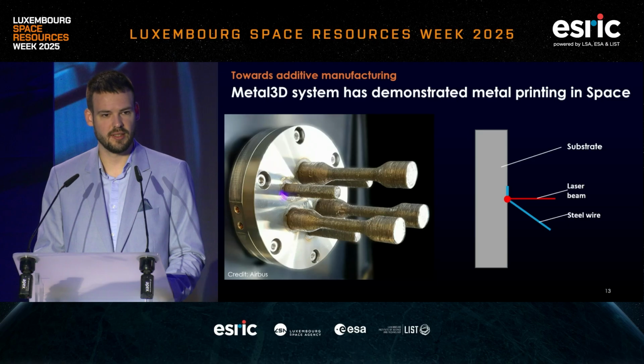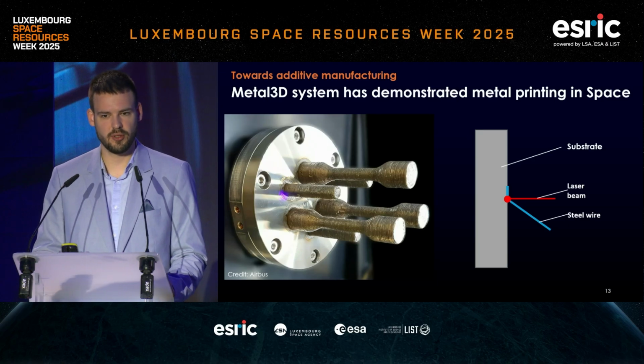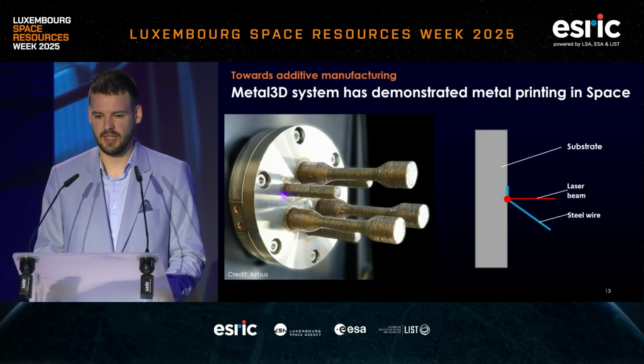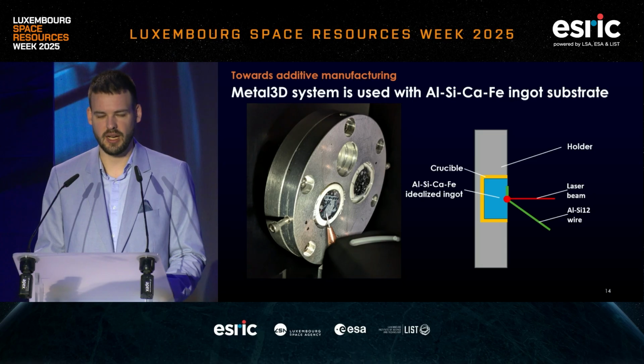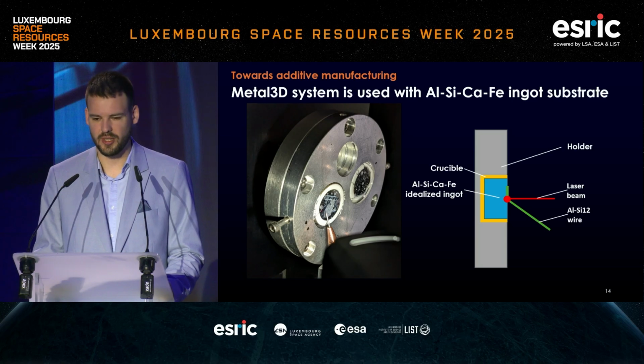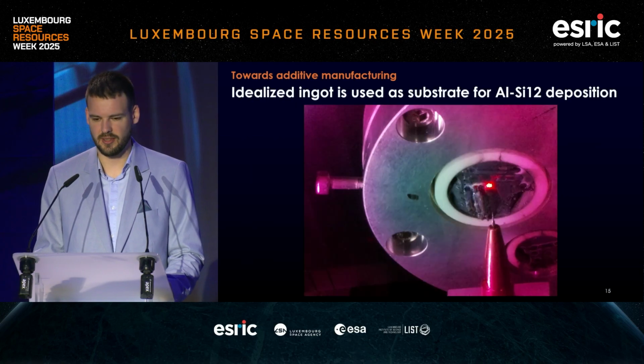So we have been using the engineering model or a prototype of the same system, and we applied it to our idealized aluminum, silicon, calcium, iron mixtures. So we replaced the substrate by an ingot of our mixture, and we replaced the wire by an aluminum silicon wire, a commercial 12% silicon aluminum alloy. And so here I'm going to show kind of the very early results from that.